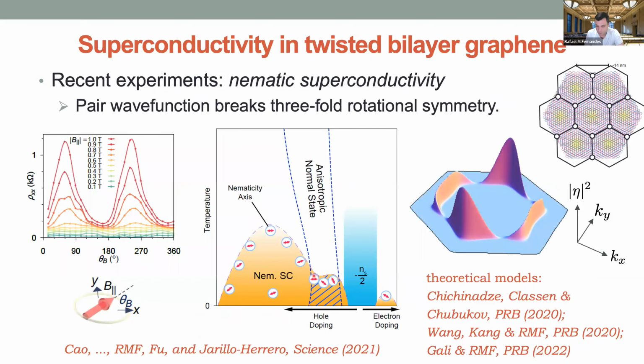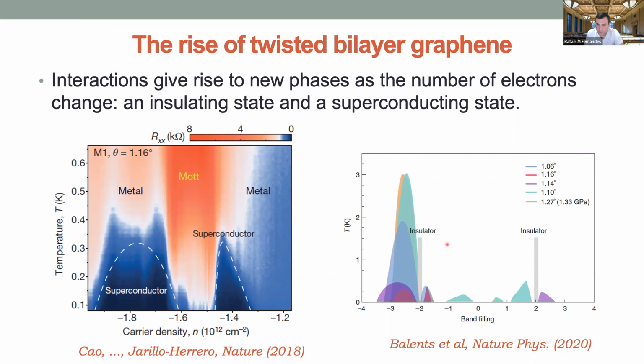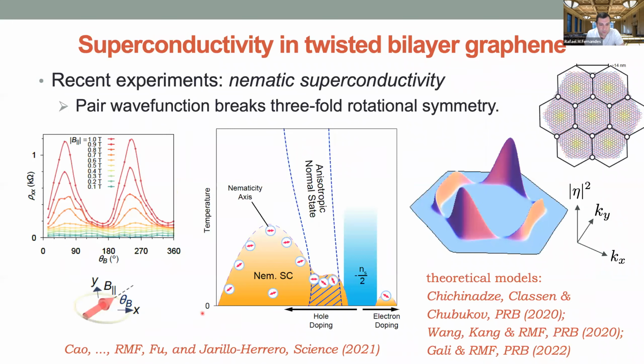Okay, let's now talk about this superconducting phase here near the hole dope side of the phase diagram. The group of Pablo Jarillo-Herrero looked at the magnetoresistance, the HC2, or the in-plane critical field and its angular dependence.